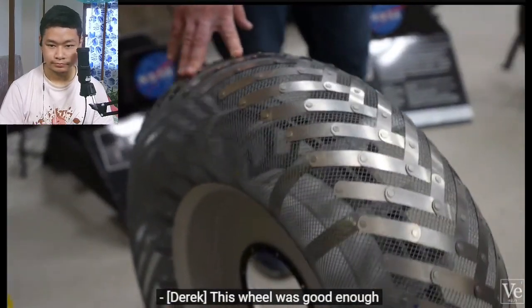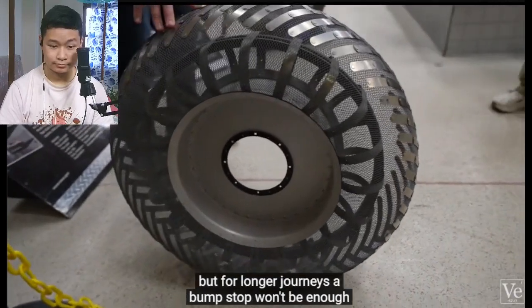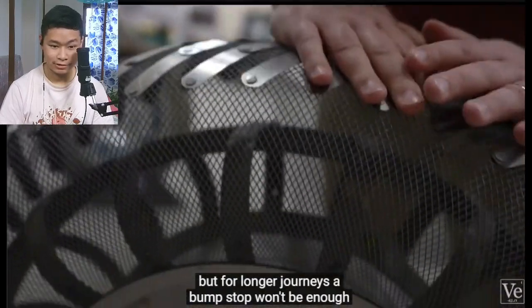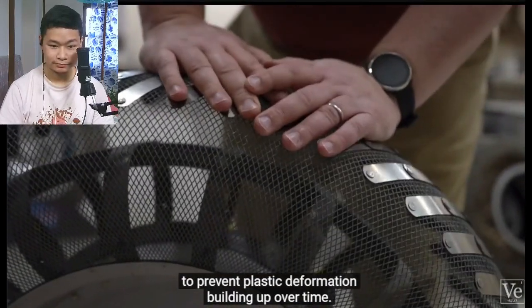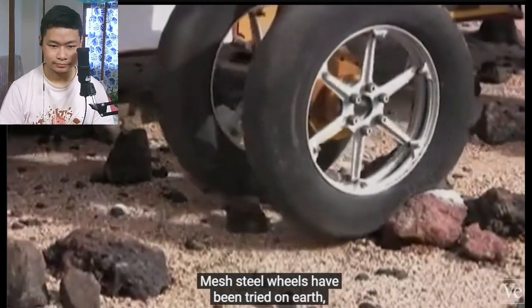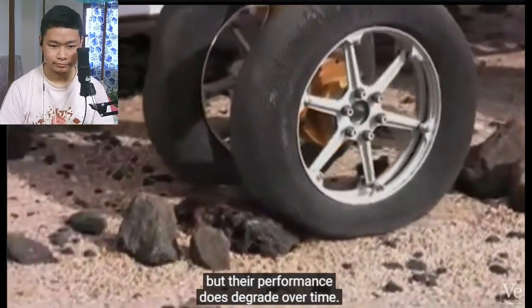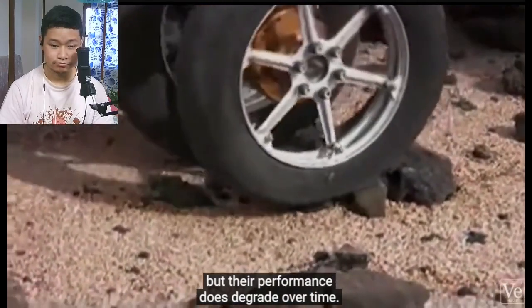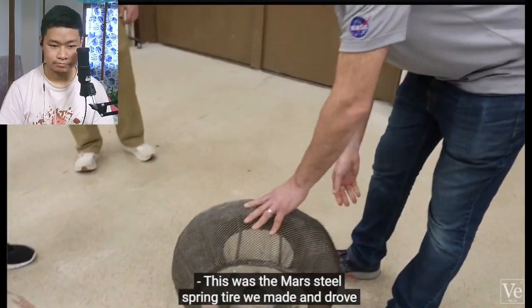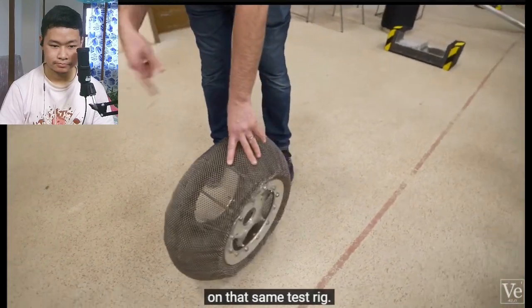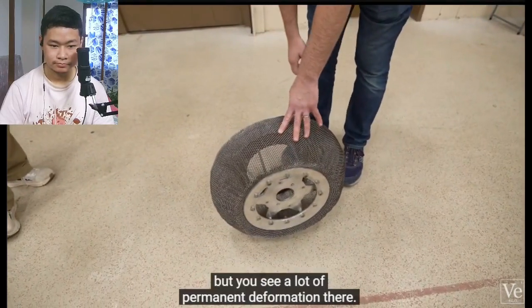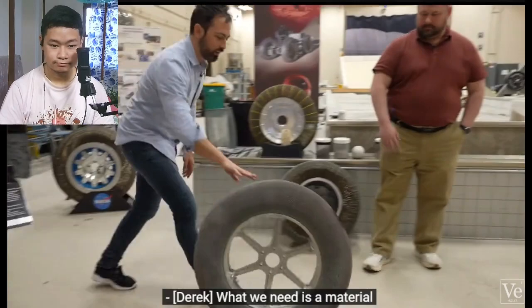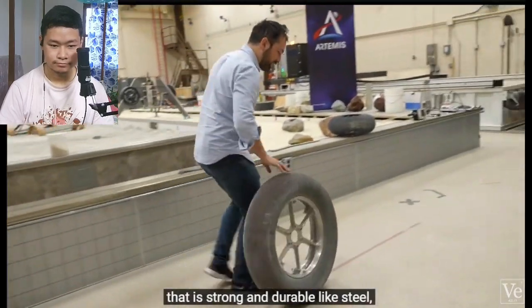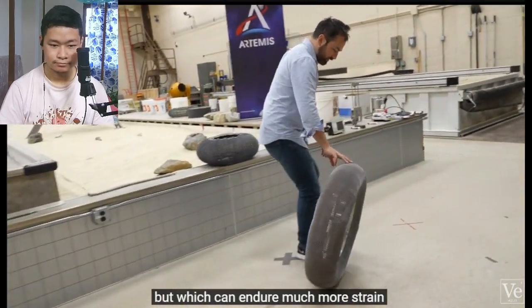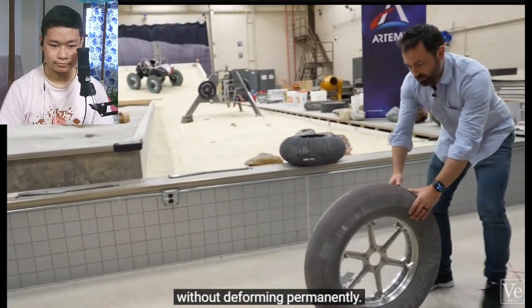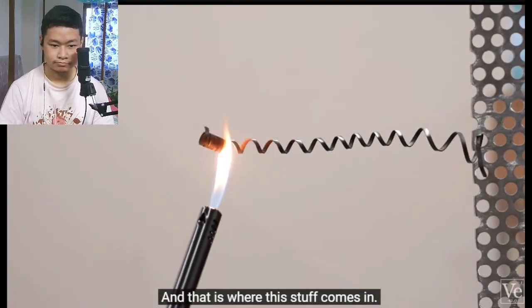This wheel was good enough for the short Apollo missions, but for longer journeys, a bump stop won't be well enough to prevent plastic deformation building up over time. Mesh steel wheels have been tried on Earth, but their performance does degrade over time. This was the Mars steel spring tire we made and drove on that same test rig, and there's no fracture, but you see a lot of permanent deformation there. What we need is a material that is strong and durable like steel, but which can endure much more strain without deforming permanently. And that is where this stuff comes in.